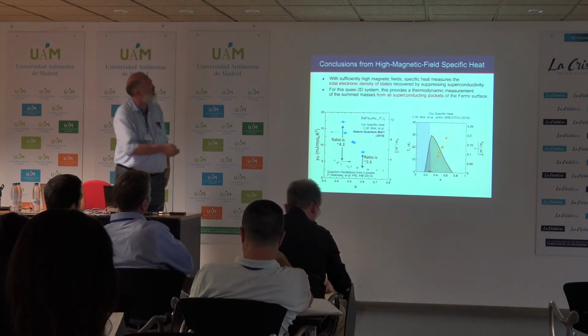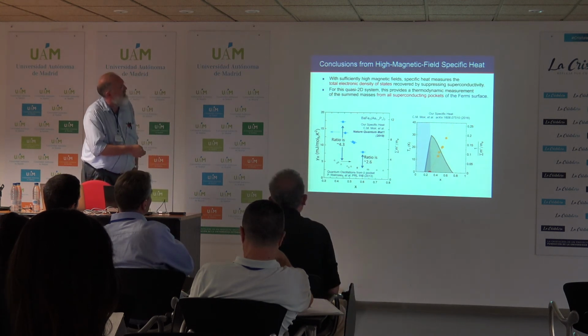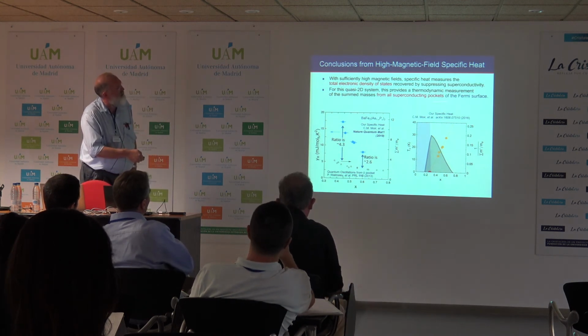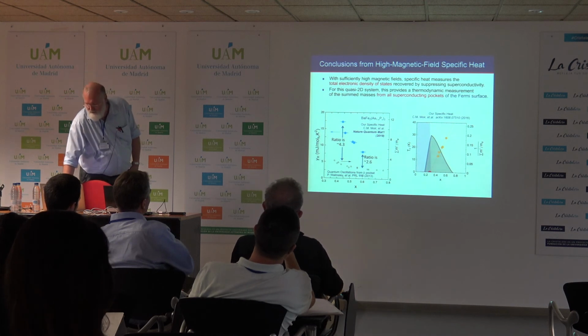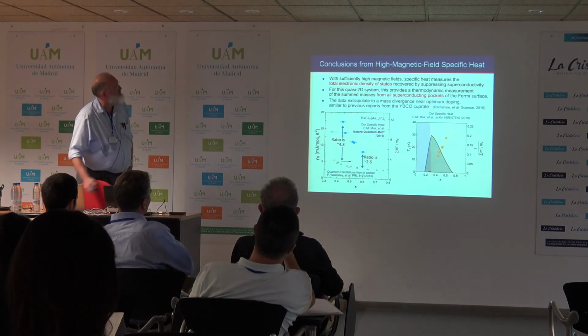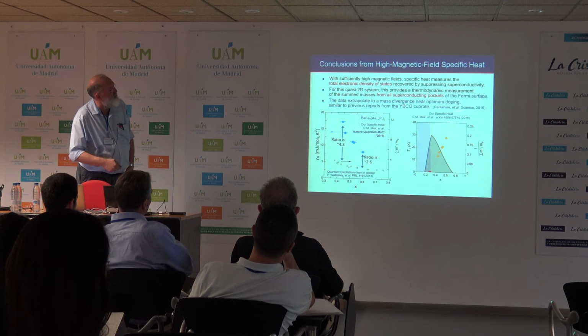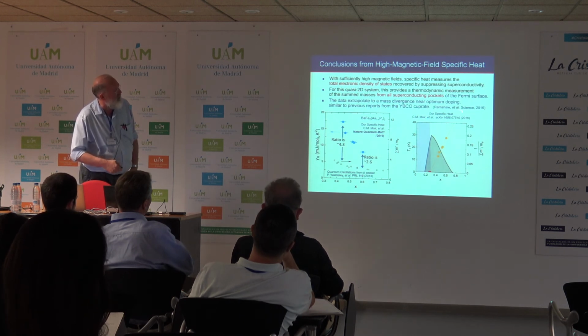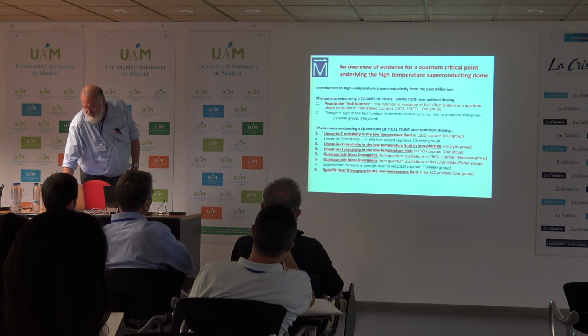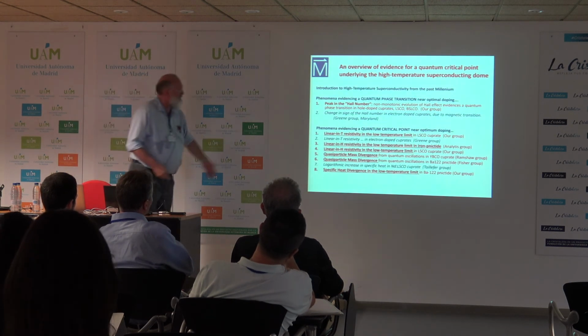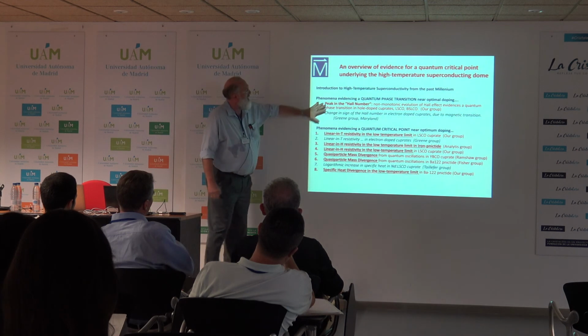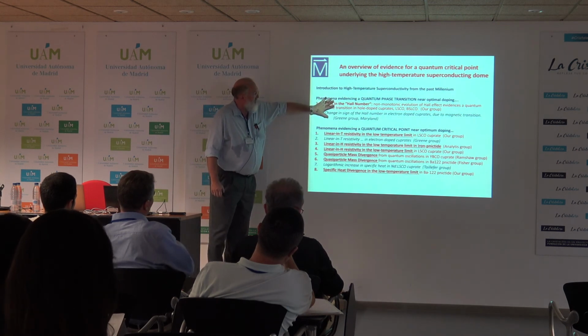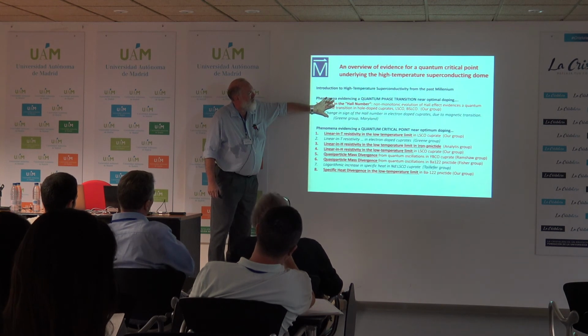So for this quasi-2D system, this provides a thermodynamic measurement of the sum masses from all the superconducting pockets of the Fermi surface. The data extrapolate to a mass divergence near optimum doping, similar to previous reports from YBCO quantum oscillations, Brad Ramshaw. And so this has been the program of the talk, attempting to give a state-of-the-art survey as best we can of evidence for phase transitions near optimum doping.